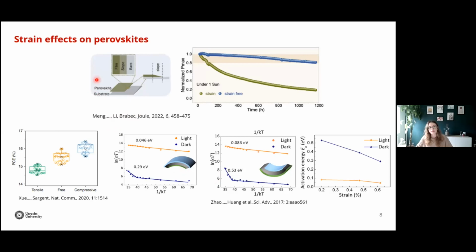And so the effect of strain on these perovskites is shown in this paper, where they look at the effect of strain on top of the film, so very far from the substrate, and then in the slope, so meaning that they probe closer to the interface between the substrate and the perovskite, and they found an increased strain in this slope.